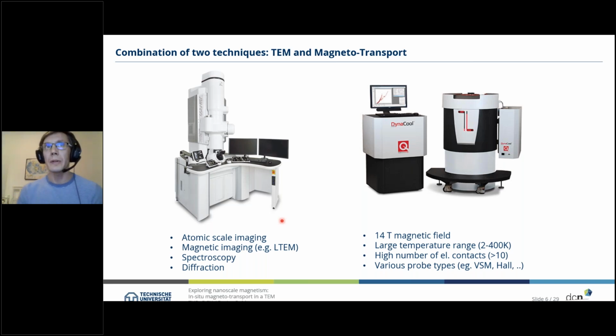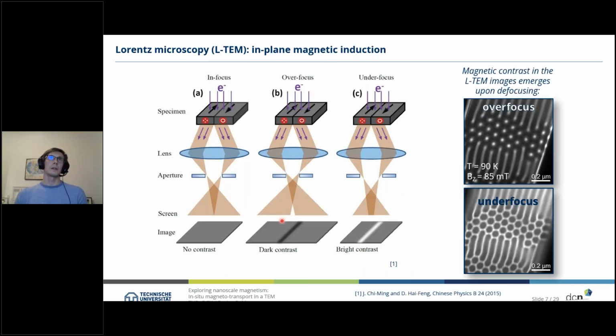So what are the important techniques which we want to combine here out of these two worlds in the beginning? On the one hand side, in the TEM, this is Lorentz microscopy, and this is a technique in TEM which is sensitive to the in-plane magnetic induction of your sample. And this is shown here on the left-hand side on the sketch for a magnetic sample with two domains. One is pointing to the back, one is pointing to the front. And due to these magnetic domains and the electrons interacting with the magnetization of that sample due to the Lorentz force, we have a deflection of the electrons, which is different depending